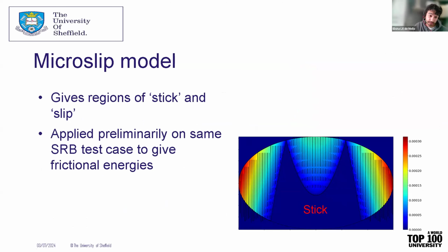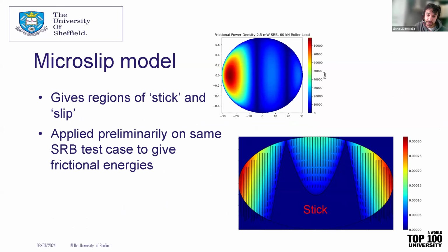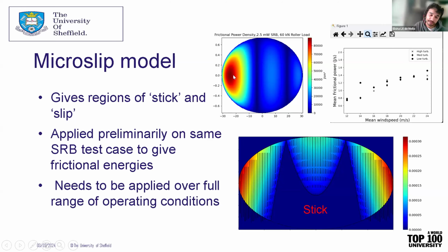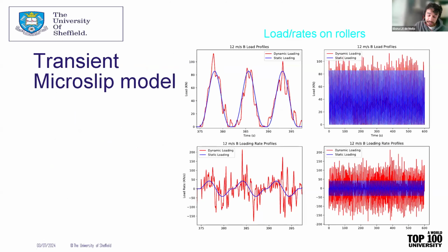And then I applied this preliminarily on a test case spherical roller bearing, the same one I used in the previous macro slip model, to have a look at frictional energies. And we can see, due to that contact angle I talked about, because the rollers are at that angle, we get differences in where frictional energy is concentrated. And to fully conclude the study, it needs to be applied over a full range of operating conditions, and I'm yet to do that. So the next thing I went on to, and as I mentioned, that microslip model is a steady state model.